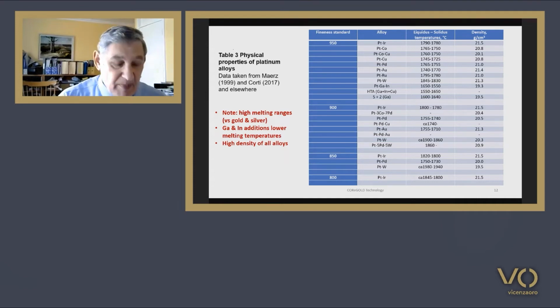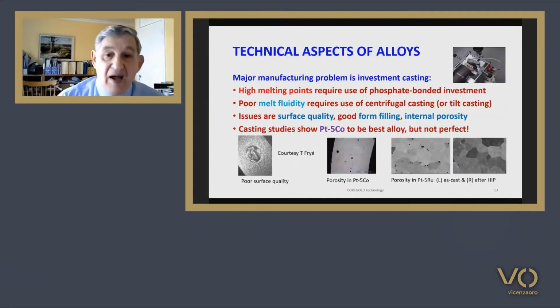The major manufacturing problems with platinum jewellery has been with investment casting. The high melting and casting temperatures require use of special phosphate bonded investment mould materials, and the poor melt fluidity requires use of centrifugal casting machines to obtain good mould fill rather than the modern gravity machines commonly used for gold and silver. The new generation of tilt casting machines are also suitable for platinum.